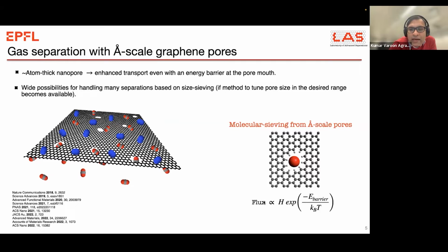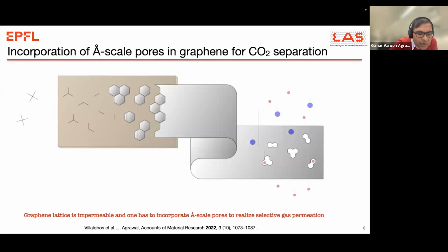All right. So if we can design holes for CO2, where the size of the holes is similar to that of CO2, we can then have selectivity from graphene membranes. And because it's just one atom thick, we can have quite fast transport. The very attractive thing for chemists or chemical engineers at EPFL, as we are, is that once we can do this, we can target many other separations. Because we can change the size of the hole, we can target different probe molecules. So the chemistry challenge for us when we started the project was, of course, that graphene doesn't have any holes. How do we create such holes? So essentially we looked into the chemistry of that.